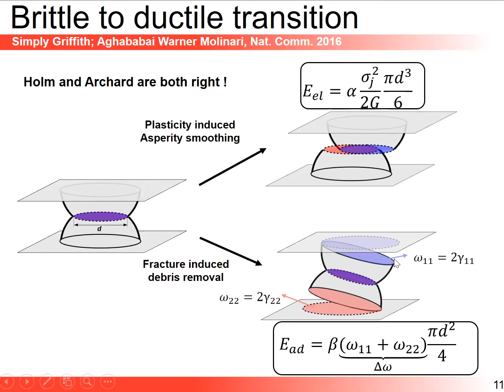That's a second mechanism, that's Archard, to create some new surfaces. There's a price to pay for this. This is the adhesive energy. You create new surfaces. So the surface energy term is called delta W, and it's going to be proportional to the new areas you need to create. And that's why you have a D squared term. And we're assuming that we cut the asperities at the base. It's a very gross approximation, but it makes our life simple. And that's why alpha and beta are fudge parameters that will not vary the findings by more than a factor of 2 or 3.